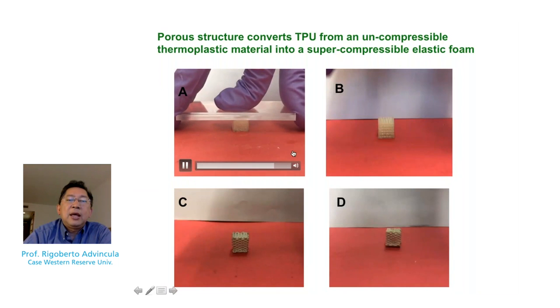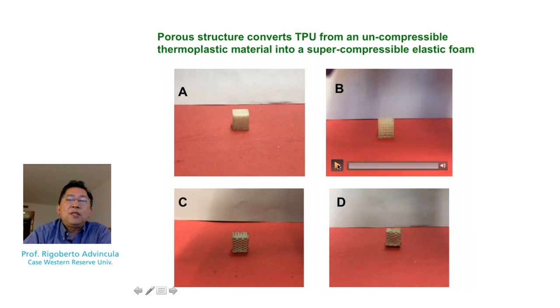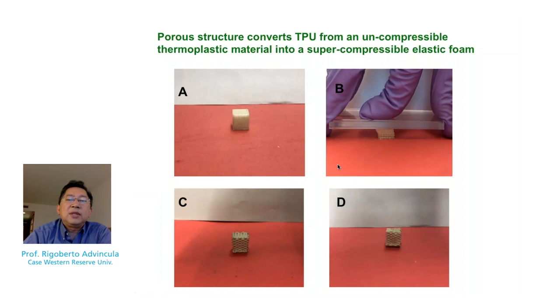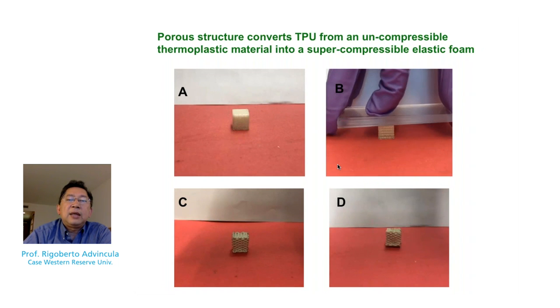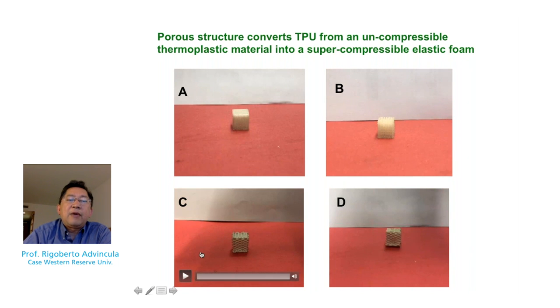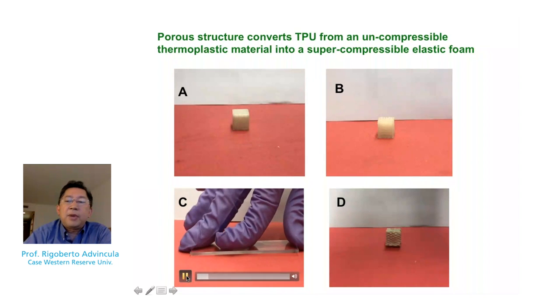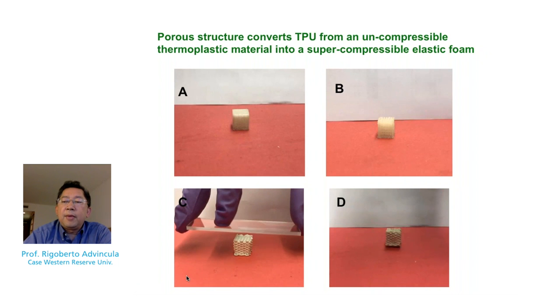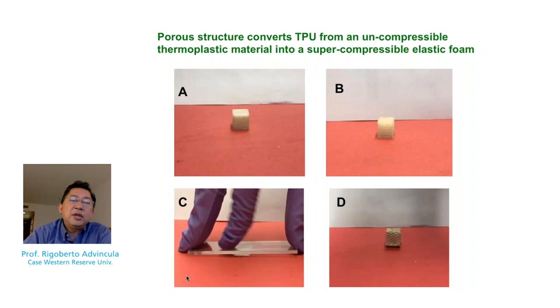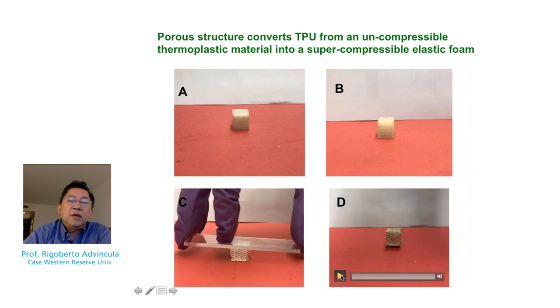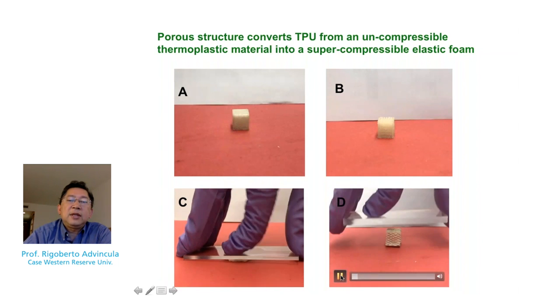So it's a plastic. And then if we change the opening size, you can see that we can compress it somewhat. Again, it still is a plastic, but you get a different mechanical property. However, by converting it, removing the nanoclay to produce a porous substance, this resulted in the formation of a highly compressible and elastic foam. And we can change the geometry and the composition to get a different elasticity as shown here.